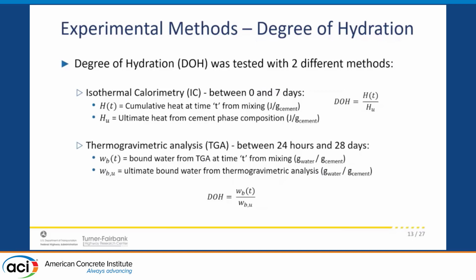Past 7 days, we relied more on TGA, which measured the weight loss after ignition of your hydrated cement sample, and then you normalize it by a reference total bound water, which represents the total amount of moisture that should be bound by the cement at full hydration.